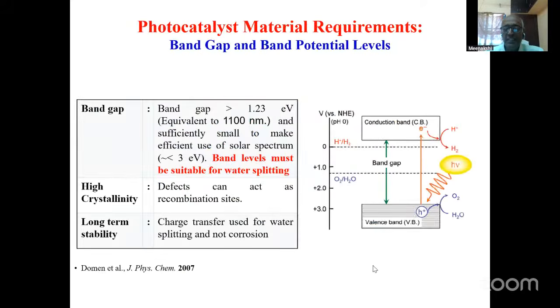Photocatalysis is very useful in splitting the water. Actually, the band gap energy required for splitting water is only 1.23 electron volt. But this energy is not the only criterion. There are so many other criteria. Band gap and band potential levels are more important. Even if you use a photocatalyst having a band gap energy of 1.23 or more, not all photocatalysts can split the water. Their band potential should be suitable for splitting the water.